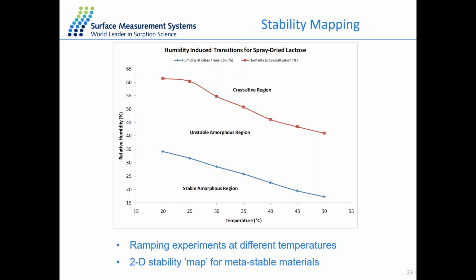So from this stability mapping, we can easily predict, at a certain condition of the material, at a certain combination of temperature and humidity, whether the sample is in a stable amorphous state, or the crystalline state, or just an unstable state that changes structure from time to time. So this stability mapping is very useful to predict the stability of the material at different conditions.